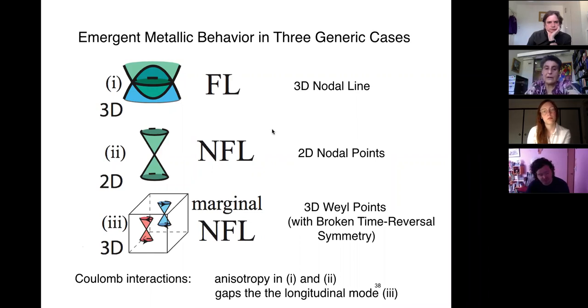I should say we did this both with and without Coulomb interactions. Without Coulomb interactions would be relevant, for example, in an elemental case, or if you had Fermi pockets nearby that would lead to strong screening. We also looked at Coulomb interactions, and they led to tremendous anisotropies here, and they gapped the longitudinal modes.